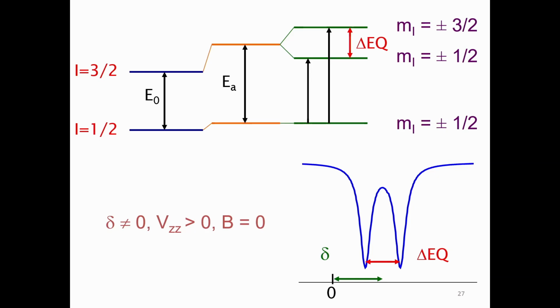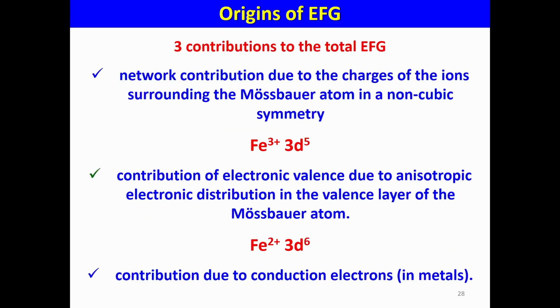And consequently, we have to distinguish different contributions. Because of course, in the case of iron 3 plus, your electronic shell is complete. Okay? And how will it interact? In the case of iron 2 plus, it's 3d6, so you have one electron which is free. Again, you can discuss in terms of equations, and you will see that if you have a sample which contains iron 3 only, the shell is complete. If you look versus temperature, it will be the same.